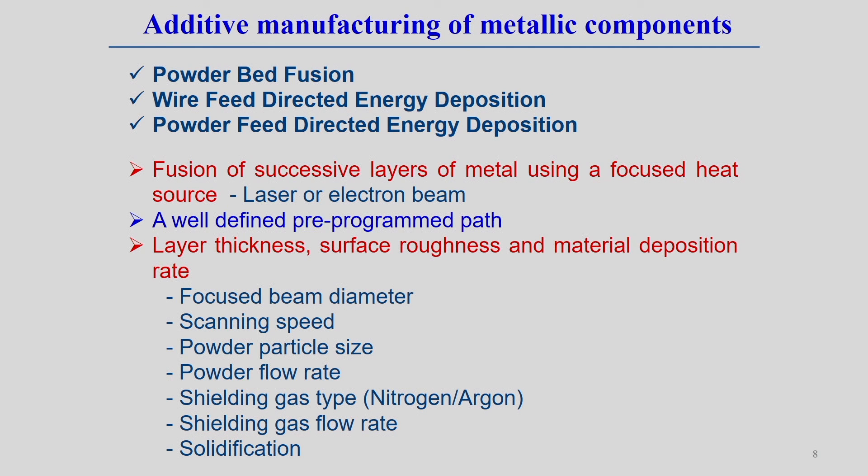Key parameters include: beam diameter, scanning speed, powder particle size, powder flow rate, shielding gas type, shielding gas flow rate, and shielding gas pressure. If the shielding gas flow rate is too high, powder can be dispersed to different areas. Solidification behavior of the powder is very important — what is the solidification time determines when the next layer can be deposited on a particular position.